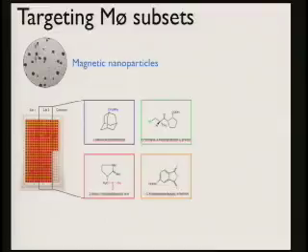So let me go back to that introductory slide. One of the first experiments that we did a couple of years ago was we asked the question whether small molecule modification of magnetic nanoparticles, which we had taken into patients at that time, based on Fe2O3, Fe3O4 magnetic cores derivatized with dextran coating, would show different in vitro behaviors when screened against cells.